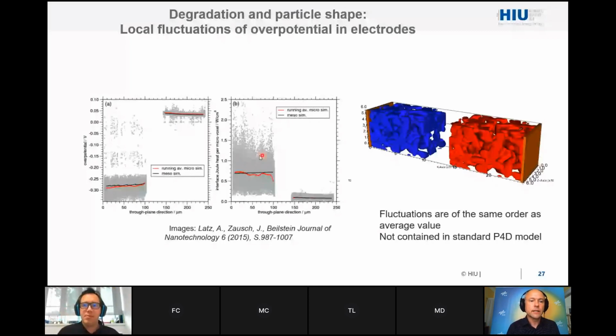And what you see here, this scattering event, is if we do cuts at each point of the cathode, and look at the average value of the overpotential in this layer, then we find these extremely scattered events. The same then for the production of heat. If we do a running average over this scattering plot here, we find this red curve, and then we compared with the P4D model. So we did an upscaling of our model, and we had an exact upscaling procedure, and we simulated the same porosity and the same tortuosity, so the same picture with the same material parameters with the P4D model, and then we found a very good agreement between the running average and the P4D model.